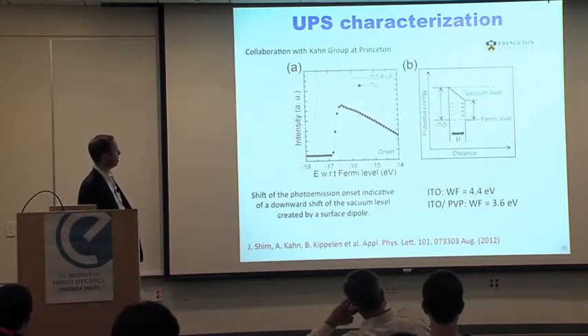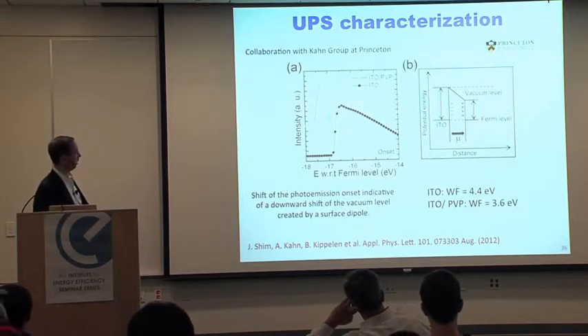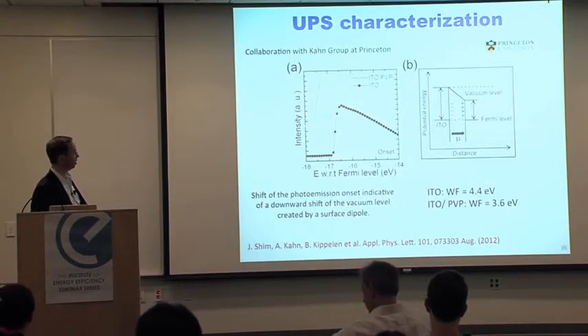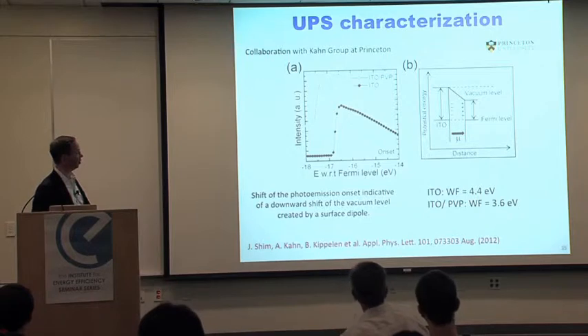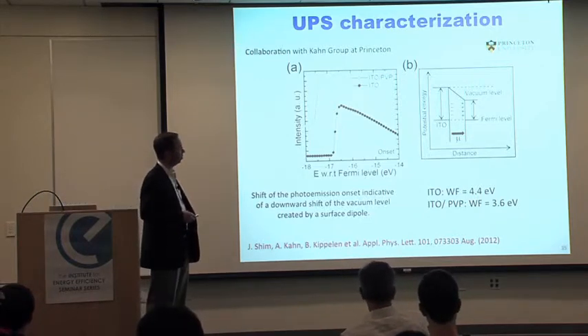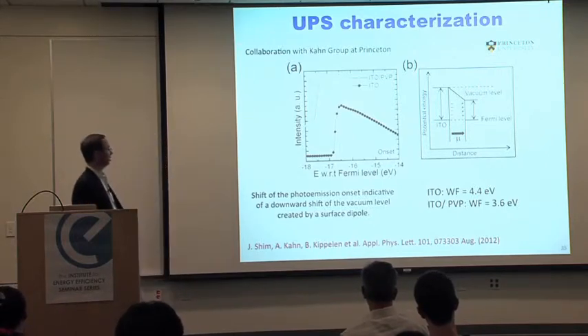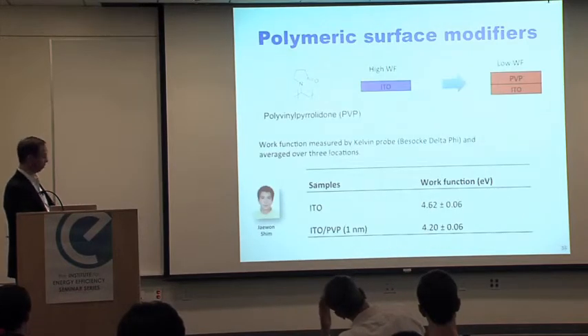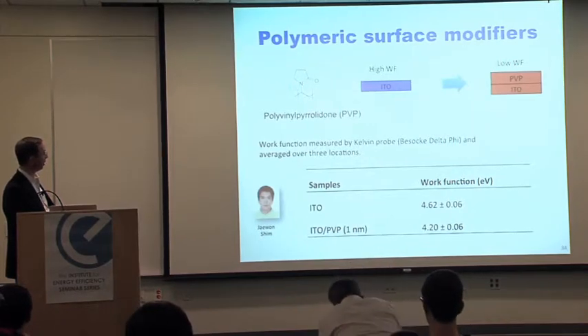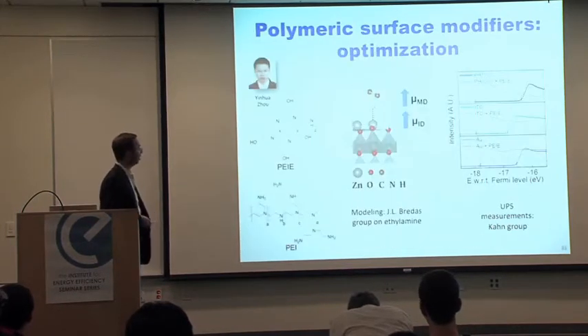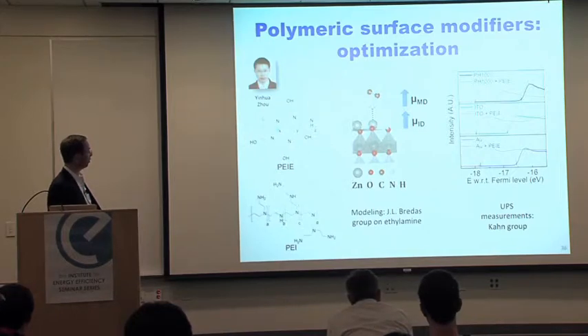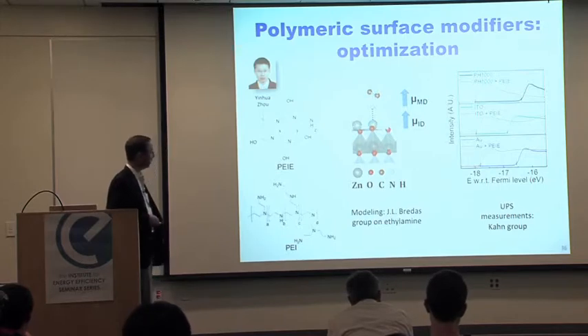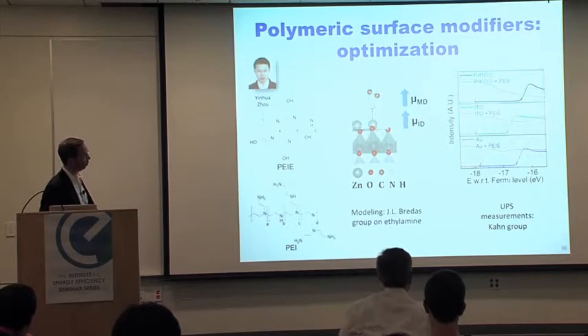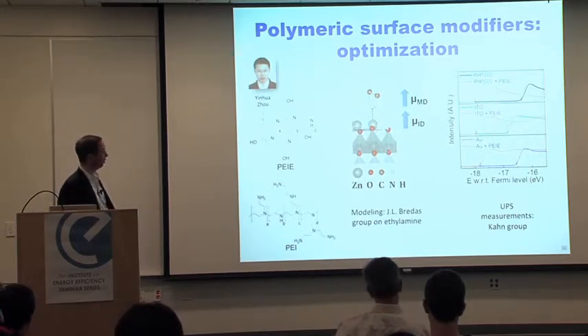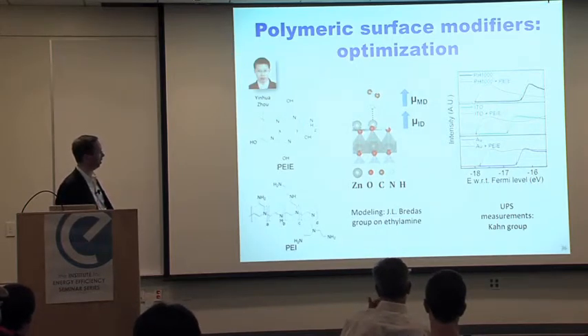We didn't quite really understand what was going on, but that's where having collaborators is very helpful, and so we sent some of these materials and samples to Antoine Kahn at Princeton, who did some UPS. The onset of these secondary photoelectrons in UPS is shifting to the left here, which is an indication of a shift down of the vacuum level, which is what you usually observe when you have formation of a surface dipole at that interface. And so back to the structure, we're trying to figure out what could cause that dipole at that interface, and the suspect here was that nitrogen. And so we started picking the Aldrich catalog and looking for a lot of molecules or polymers that contain these amines, and one of them was PEI. And when we now modified the surface of ITO with one of these polymers that contained a large number of amines, you can see now the shift is even larger.